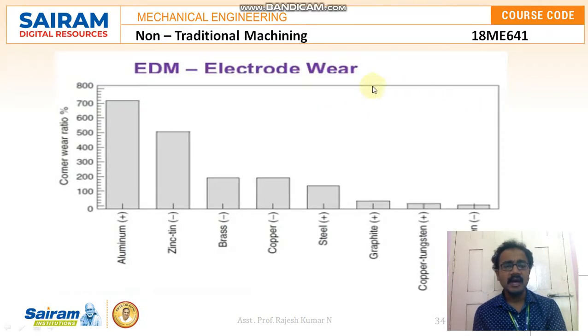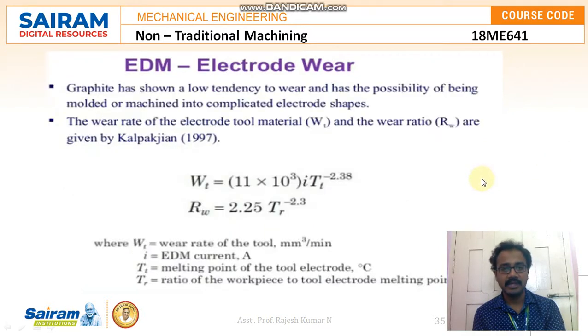And this is the electrode wear for the different materials. Among that, aluminium stands first with a corner wear ratio percentage of 700, you can see. For zinc, it is around 500. For brass, it is around 200. Copper almost 200, and steel is around 150 to 180. Graphite, you can see, hardly 20-30 corner wear ratio, and copper tungsten again less than 10 percent, silver tungsten again less than 10 percent.